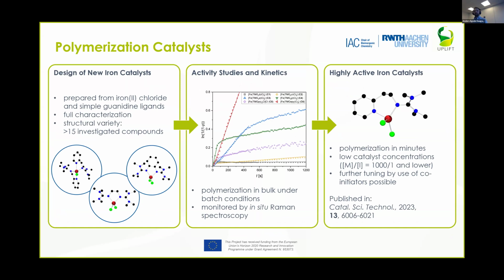These different types of iron catalysts are prepared relatively straightforwardly. There's been a range of these catalysts investigated, so more than 15 different compounds, and it's clear that there is a very dramatic increase in activity for these systems, and they are highly active. Multiple of these have already been published, and as I said, one of them has been scaled up and tested for continuous production in reactive extrusion.